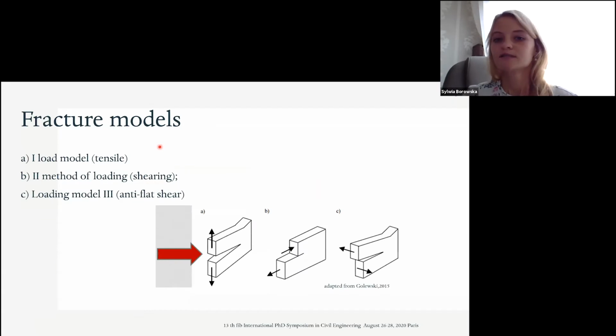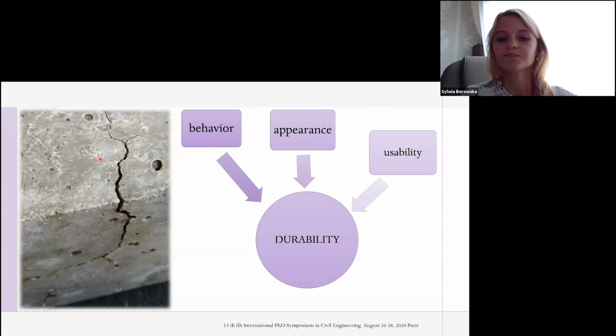In my research, I focus on stress intensity factor, fracture energy, and crack mouth opening displacement. This paper presents the results of experiments concerning determination of the resistance to cracking according to the first model of fracture, tensile and bending. The key point here is the durability of high-strength and high-strength fiber reinforced concrete.